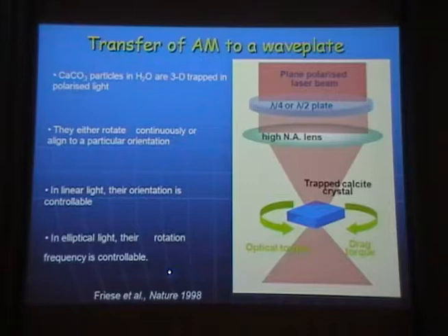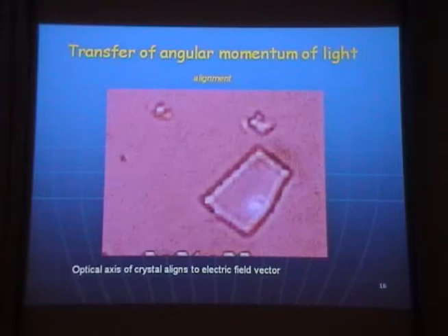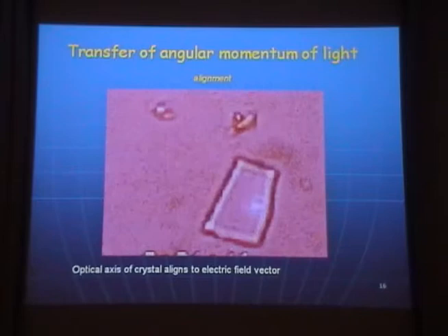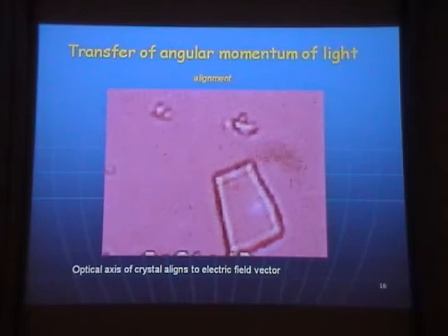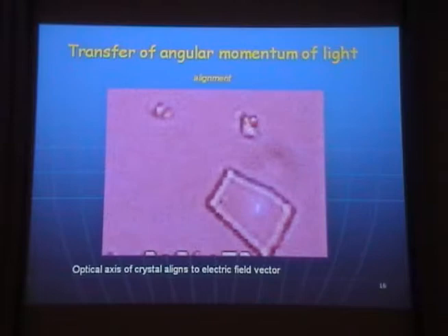So here is a shard of calcite crystal. It's rather large and therefore it's not trapped three-dimensionally. And what we are doing is we are aligning it with the axis of lambda over 2 plate. So I'm turning lambda over 2 plate and my crystal is following the rotation of my lambda over 2 plate. So the optics axis of the crystal aligns to the electric field vector.